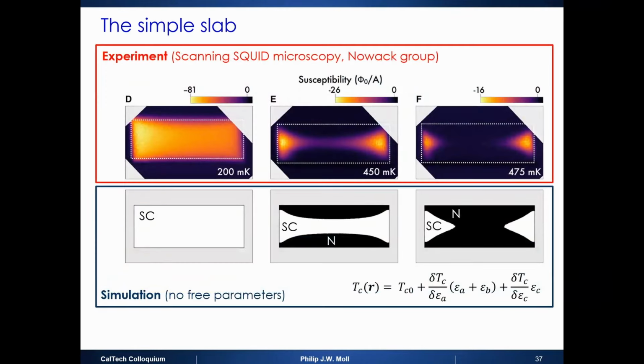So you would expect a very interesting landscape of TC in this object, and that's what you see. These are actual scanning SQUID measurements of these slabs done by my friend Katja Nowack at Cornell. If you go to low enough temperatures, everything lights up. That means there's complete Meissner shielding, that the thing is completely superconducting. That's good, that's what it's supposed to do.